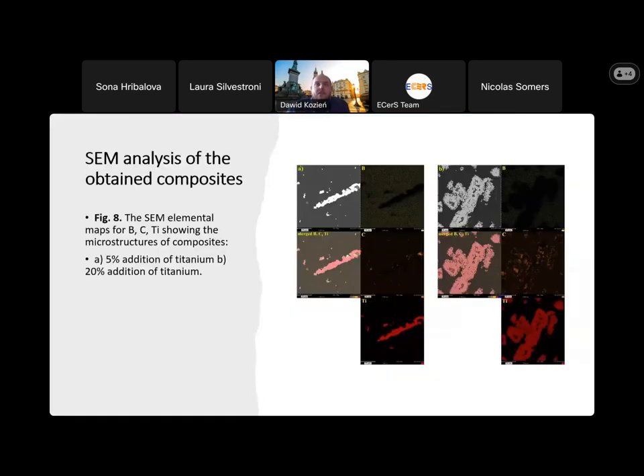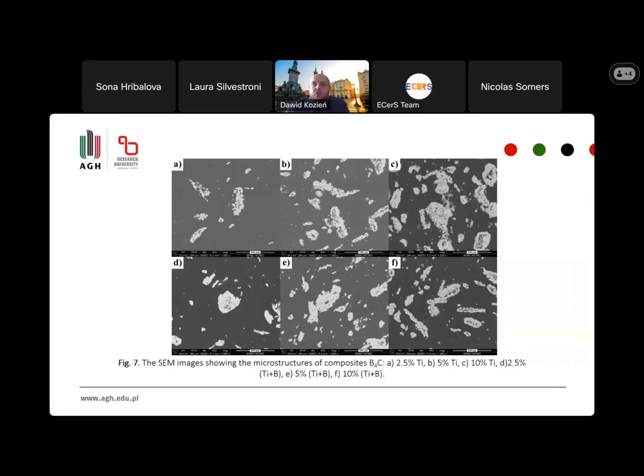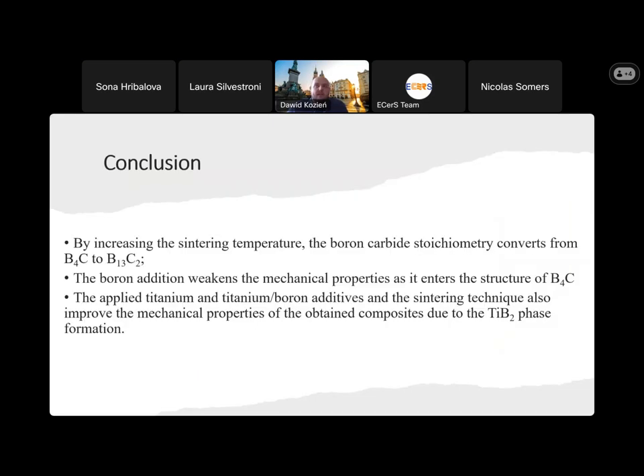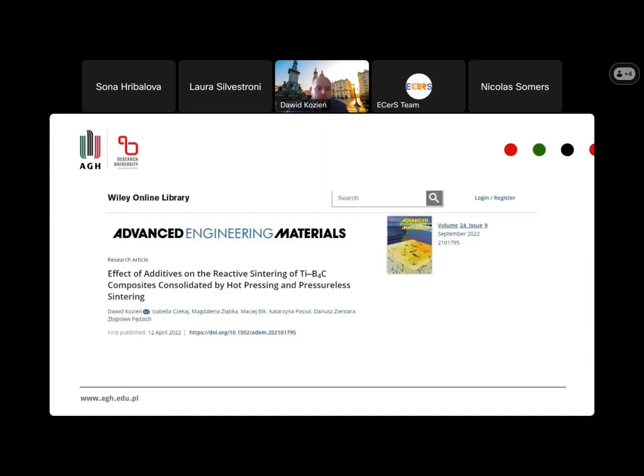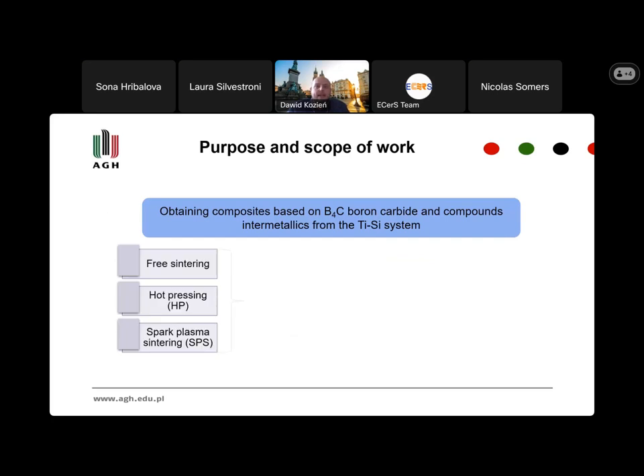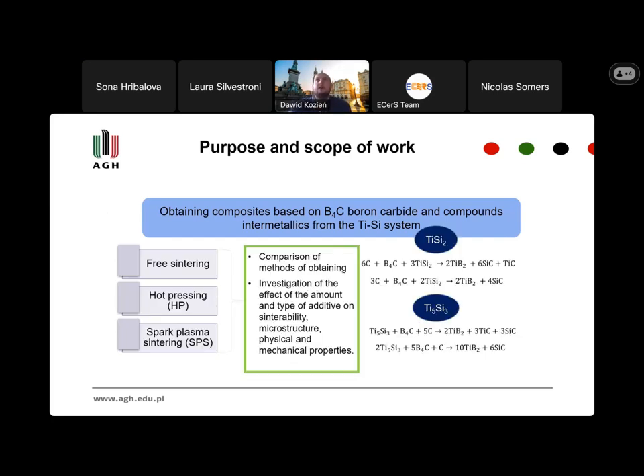We can see the table of phase formation and some analysis. It looks quite good, and we have some very interesting results. By increasing the sintering temperature, the boron carbide stoichiometry converts from B4C to B13C2. The boron additives weaken the mechanical properties as they enter the structure of the boron carbide, and the titanium and titanium-boron additives and the sintering technique also improve the mechanical properties of the obtained composite due to titanium diboride phase formation.